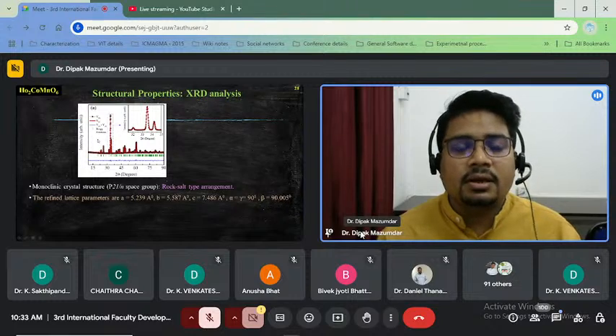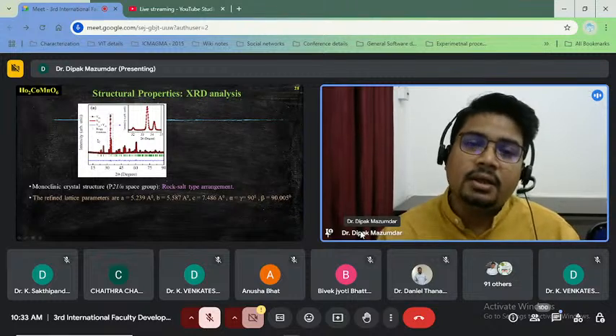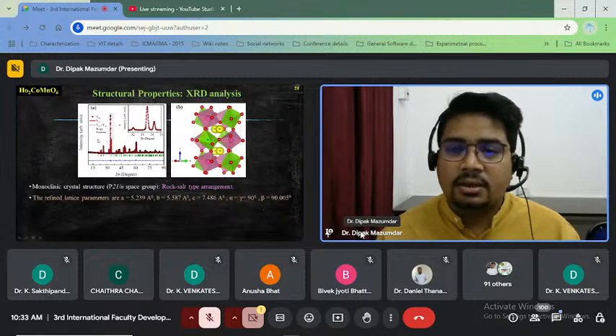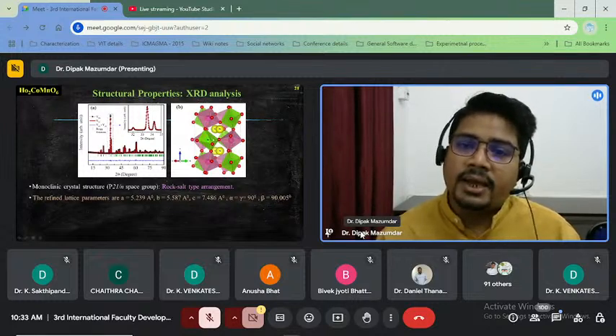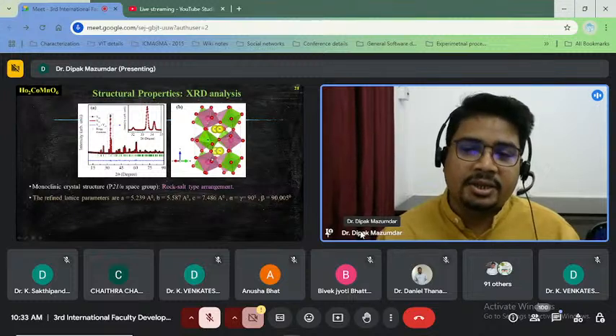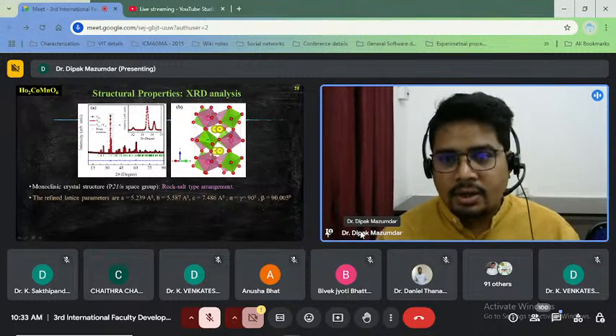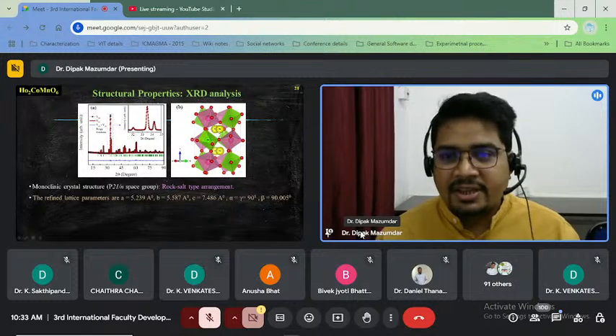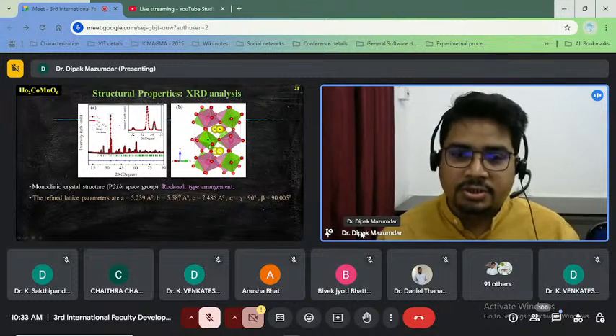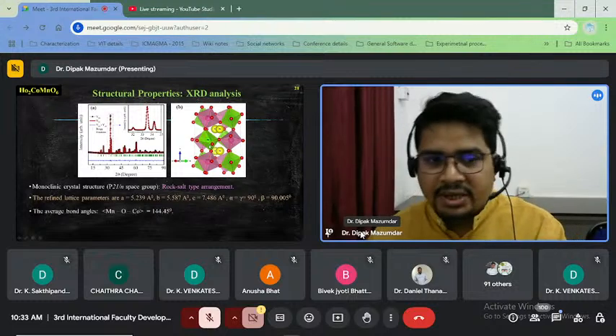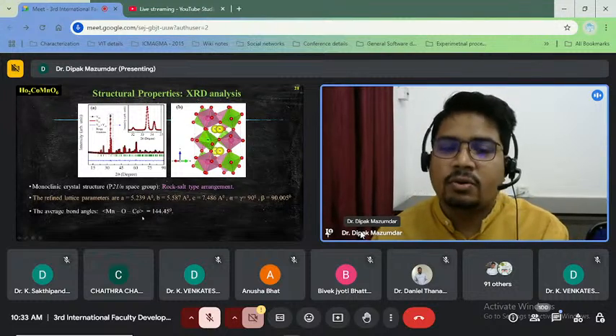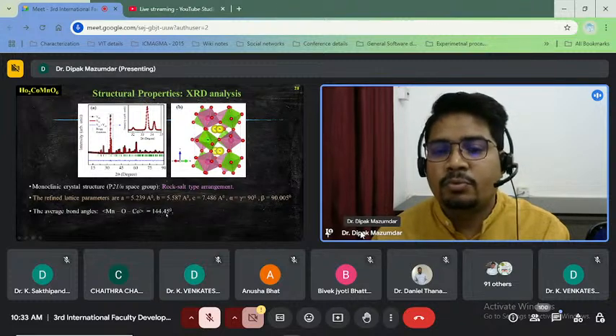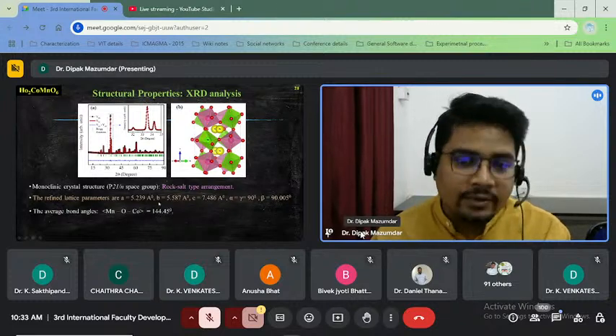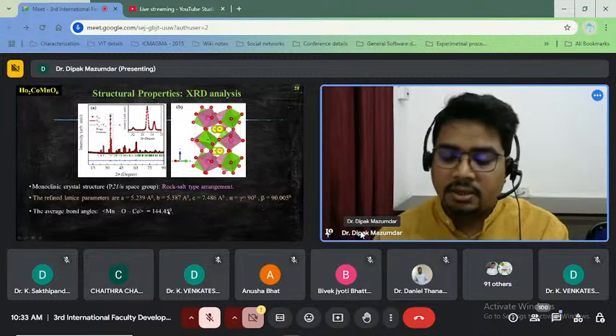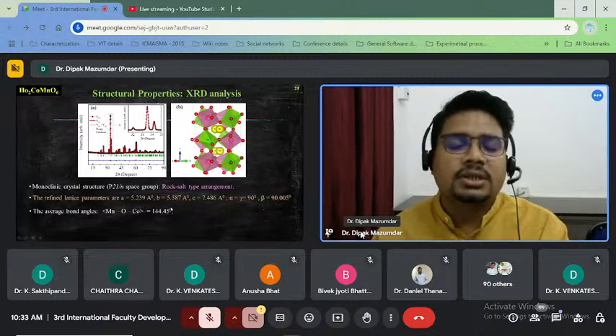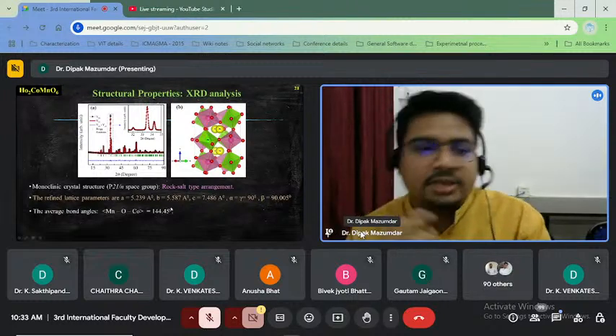Next, from this crystallographic data, we have constructed the crystal structure, which looks like this. We can see that manganese and cobalt are in a rock-salt arrangement, as I already told, and the holmium is sandwiched between the spaces of these octahedral positions. From this picture, we can determine the bond angle between manganese and cobalt, which is around 144.45 degrees, deviated from the ideal 180 degrees, which can give rise to several interesting, fascinating magnetic ground states also.